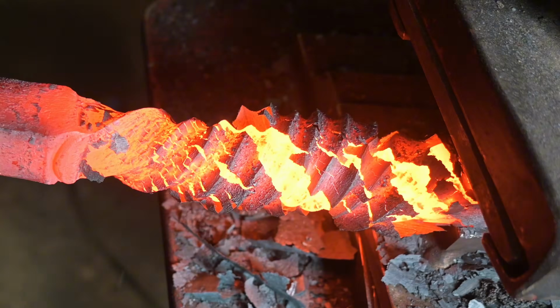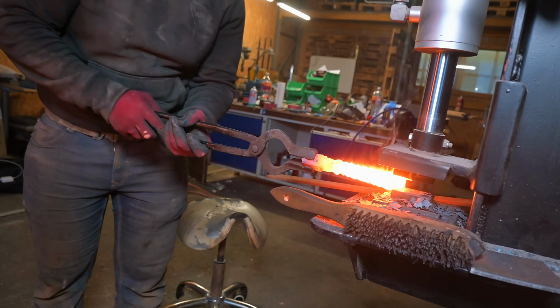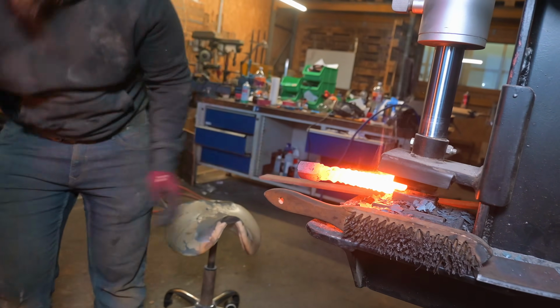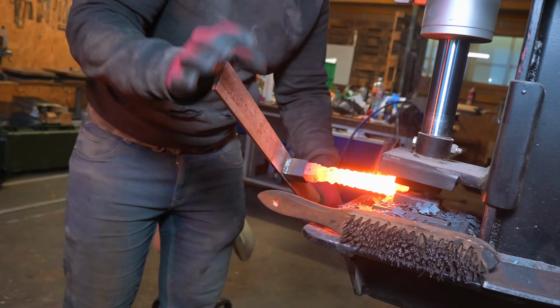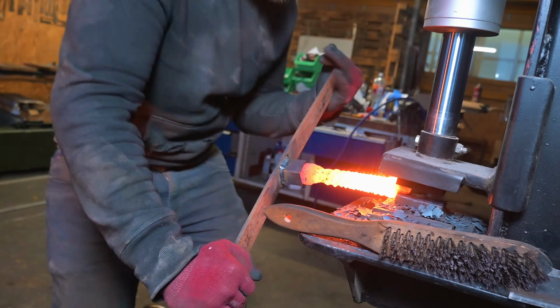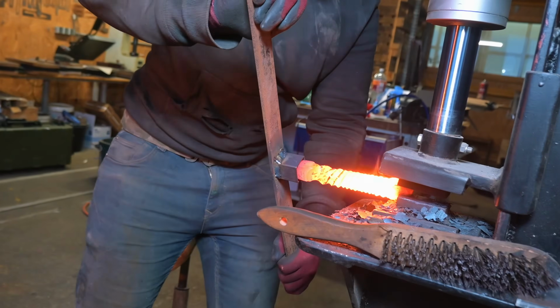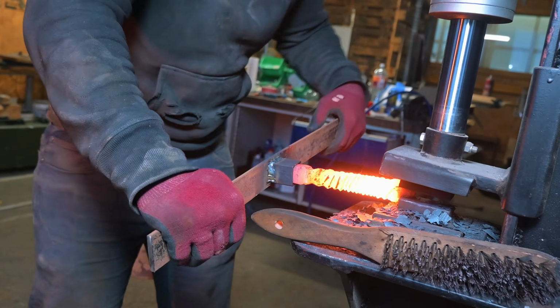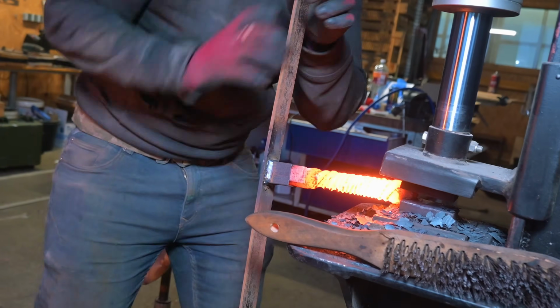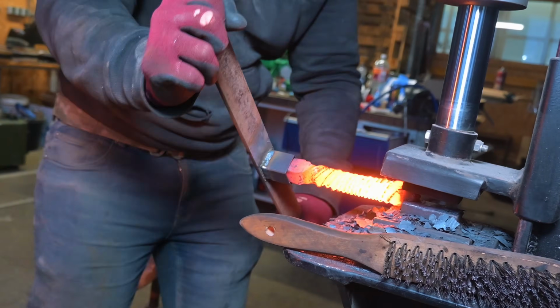Maybe there were too many voids in between, which caused bad welds and pockets inside of that steel that scaled up. What I also noticed when I was rewatching the footage is that I pressed too much in the beginning, which deformed the canister, and that could have led to pressing into the material and splitting it.